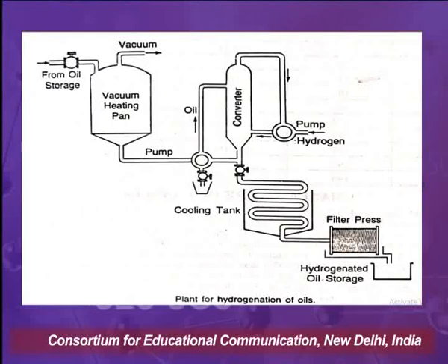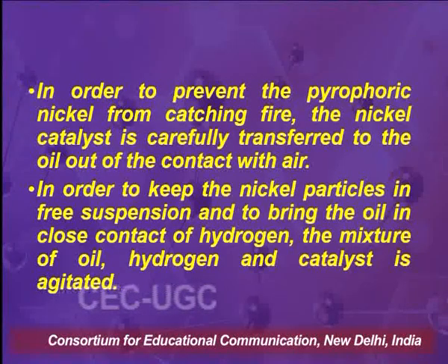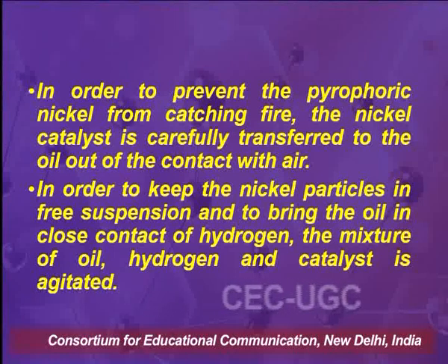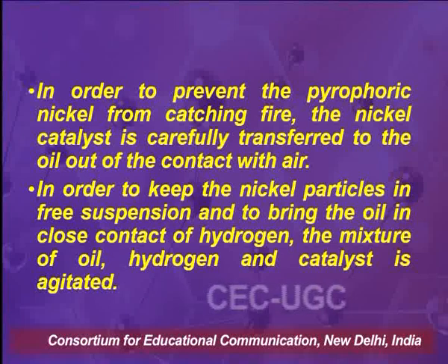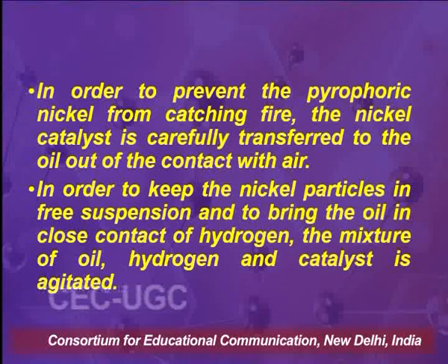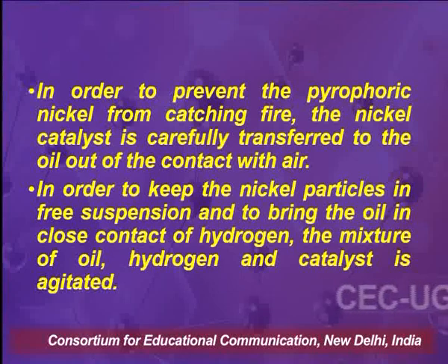This is the plant for hydrogenation of oils. Here in the right corner is the tank where the hydrogenated oil is collected. In order to prevent the pyrophoric nickel from catching fire, the nickel catalyst is carefully transferred to the oil out of contact with air. In order to keep the nickel particles in free suspension and to bring the oil in close contact with hydrogen, the mixture of oil, hydrogen and catalyst is agitated.